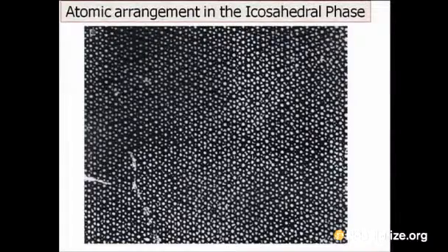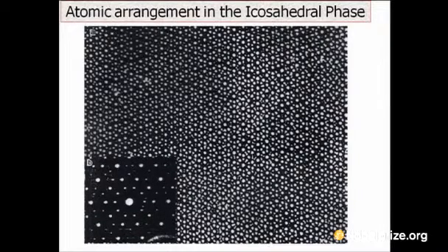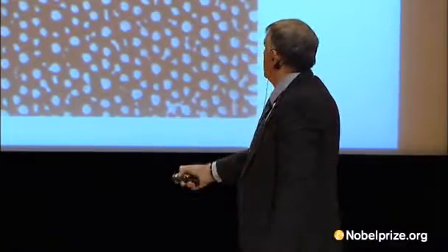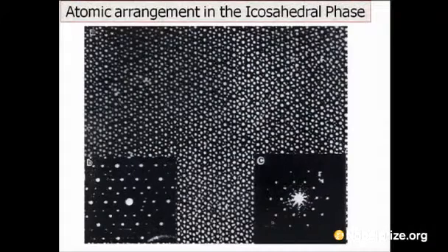And they did a wonderful experiment. You see, this is the diffraction pattern from this crystal. But what you can do is take a slide with this crystal and make an optical diffraction. Just put the slide here, put a laser beam here, shine through, and what you get is this diffraction pattern. This is optical diffraction. So the mathematicians among you will say, well, what's the big deal? You do a Fourier transform from this to this. You do a Fourier transform back to this. It should be the same thing, of course.